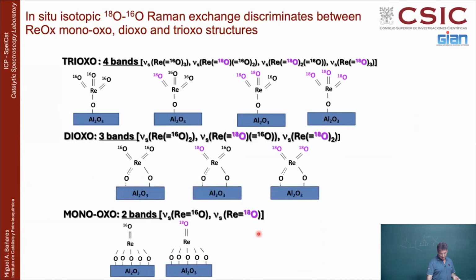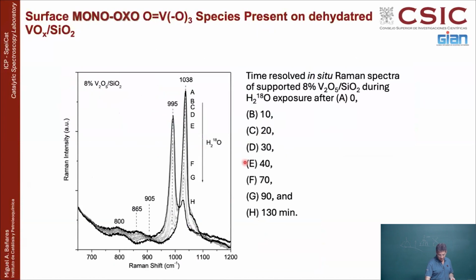And of course, if you make isotopic exchange, the possibilities are that none of them is replaced, or one of them is oxygen-18. So in addition to the very many peaks that you get for a trioxo, if you get oxygen exchange, that will be crazy. So the simplest case is you make oxygen exchange on a monooxo species. Then basically you have the vanadyl oxygen-16 or vanadyl oxygen-18. In this case, they are just flowing through a vapor of water, which is H2O with O-18. So little by little, the water is replacing the oxygen in the system with oxygen-18. Basically what happens is that you are losing the oxygen-16 and you are getting the oxygen-18. So it's a very elegant experiment, which very nicely illustrates that it's a single oxo group. One is disappearing and the other is appearing. So basically you replace one by the other.